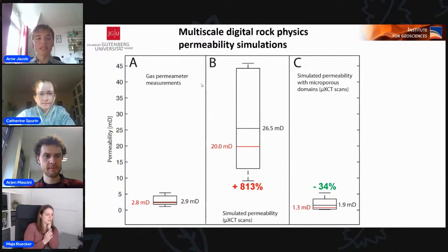And what you can see is that the range of values is far too high in the middle. You can see that the values are between like 7 millidarcies and 50 millidarcies. And have you also compared the error here to the sensitivity of your input parameters? We do this in the next publication, which is hopefully going out in the next month. But we're still on it. So you can expect that it will come.